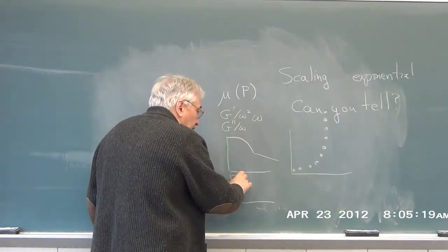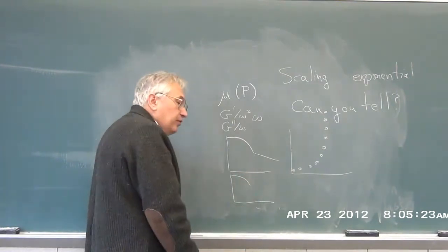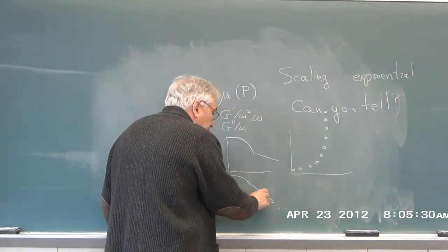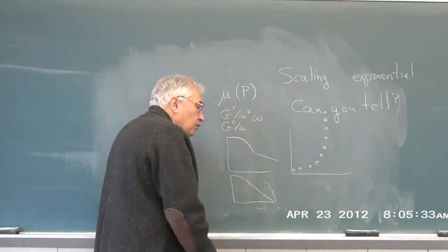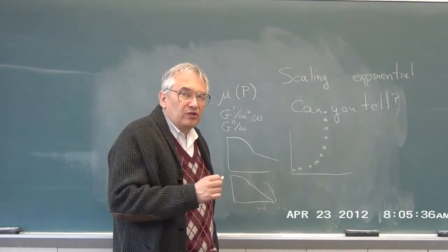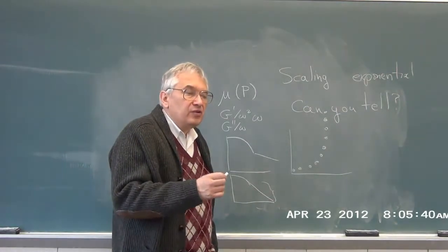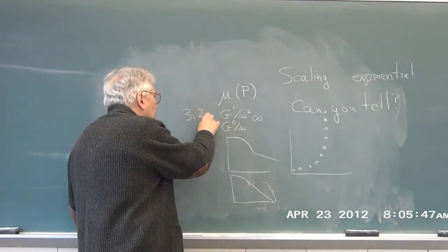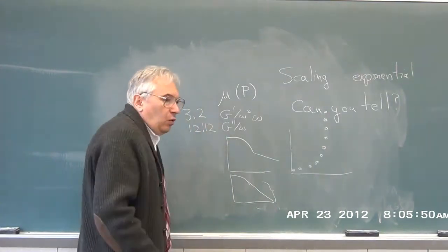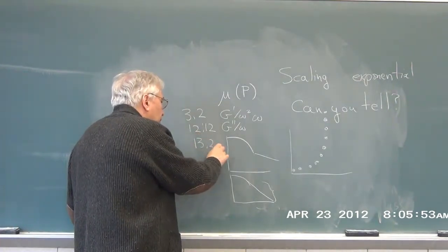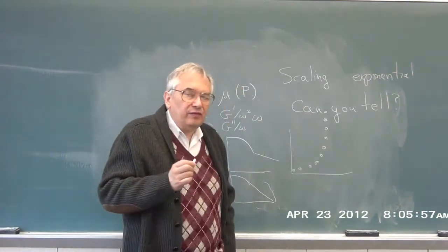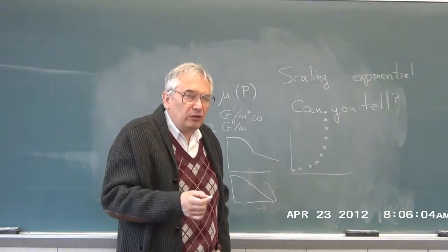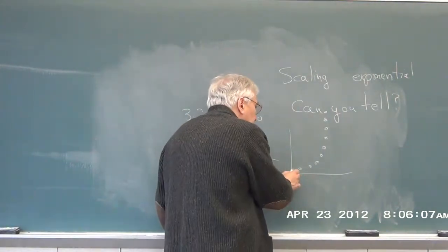we had a region which was quite clearly, on a log-log plot, a stretched exponential, and a consequent region which was very clearly a power law, and this would go over a fair number of orders of magnitude, so there was no question that on a log-log plot you really were looking at a straight line to very great extent. You can see these in figures such as 3.2, 12.12, or 13.2. You can actually very clearly tell when you have a stretched exponential, when you have a power law, and you have measurements which on a log-log plot, like these dots, very clearly lie on a smooth curve.